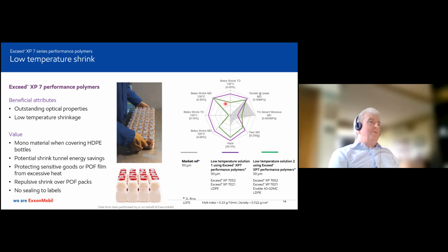But you notice though that even with the addition of that medium density resin, we now have to drive the shrink tunnel temperature up to 130, which is still very low compared to what people normally run shrink tunnels at, but it's still not as low as the 120, which you can do without the medium density inclusion.